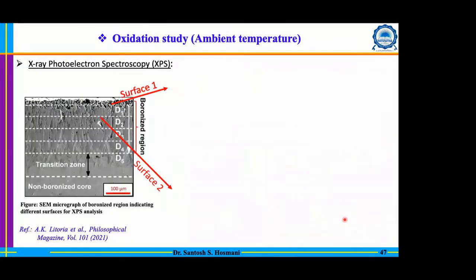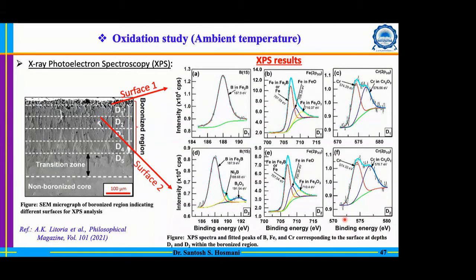Now we also studied the oxidation resistance, and for that we removed the material layer by layer. The purpose was to see, after deterioration of the surface, how the fresh surface reacts with the ambient environment. For that purpose, we removed the layers one by one and took XPS, X-ray photoelectron spectroscopy. This XPS gives us the chemical information of the elements at different depths, and that helps us understand how the oxidation response occurred.